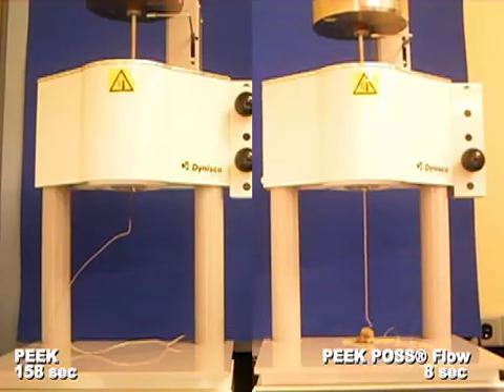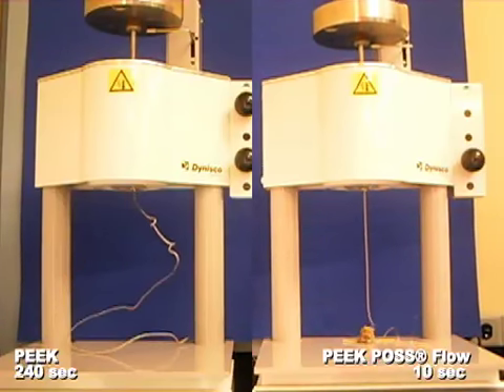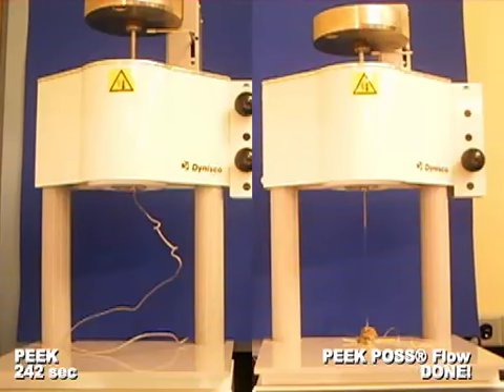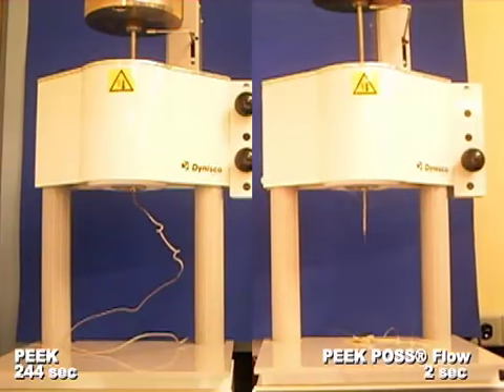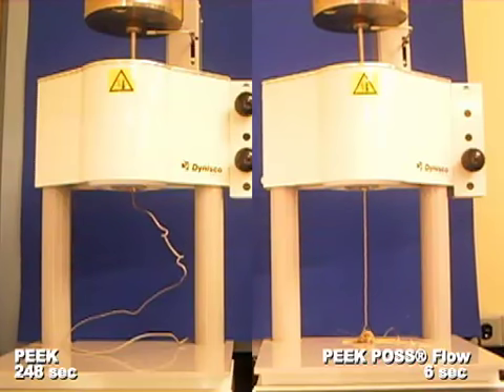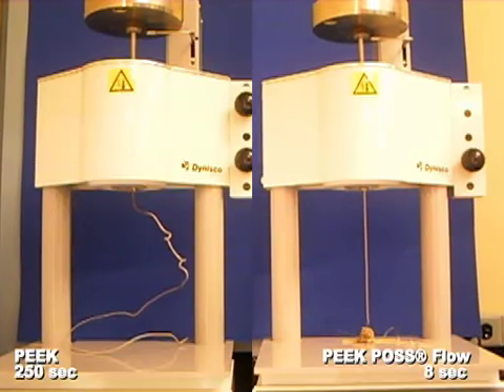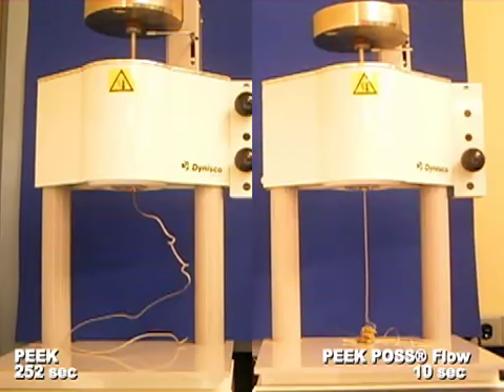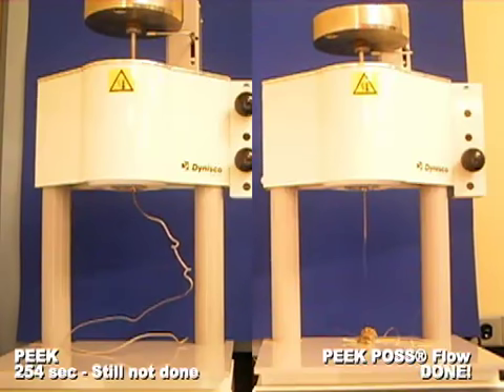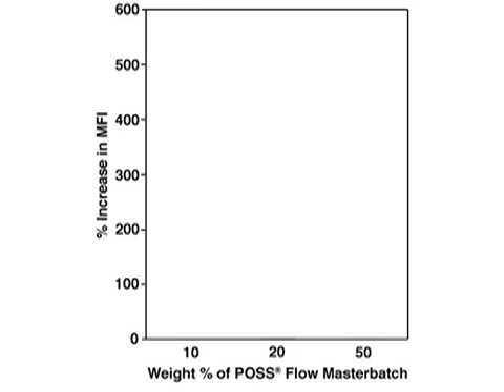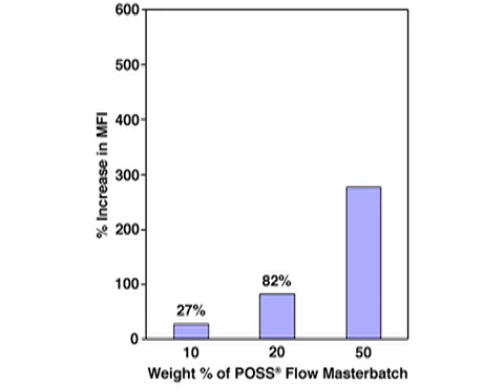It's easy to see how much the flow is improved when the PEEK is blended with POSS flow modifiers to make a master batch. Let's see that again. And when the POSS cools and re-solidifies in the polymer, it provides nanoscale reinforcement. High molecular weight PEEK is typically blended with the POSS flow master batch at from 10 to 20 weight%.